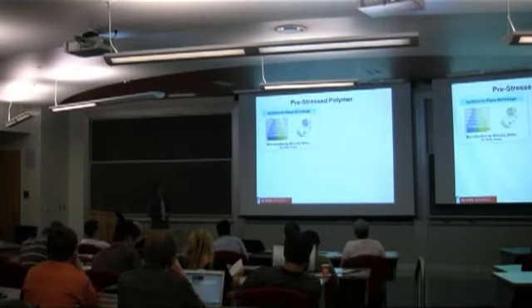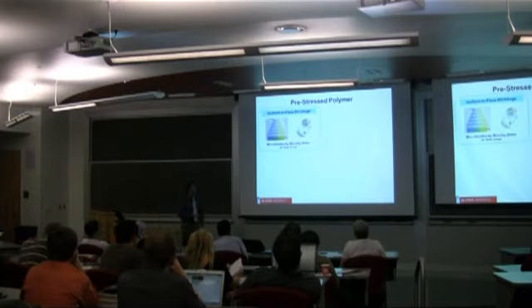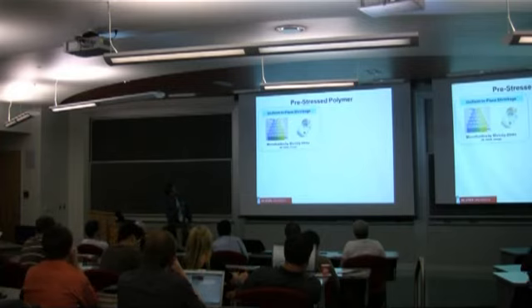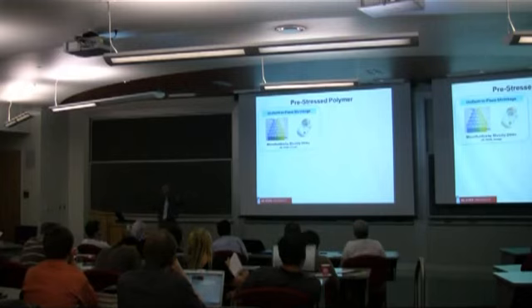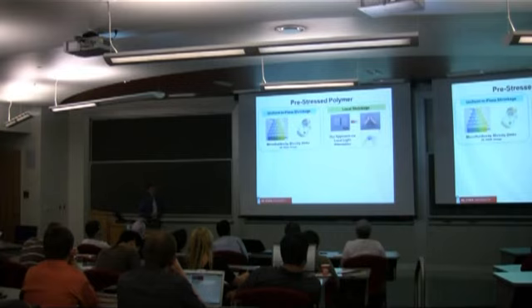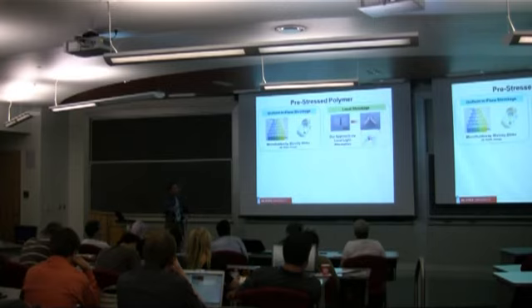And so we're not the first ones to realize the utility of this fun children's toy. Michelle Khine's group in California came up with a way of making microfluidic channels by printing on a large area and then shrinking the features down, making them micro scale. Our idea again is to use localized heating, so you can see where the black ink is, you get some localized shrinkage, and of course the material has to go somewhere so it gets thicker.